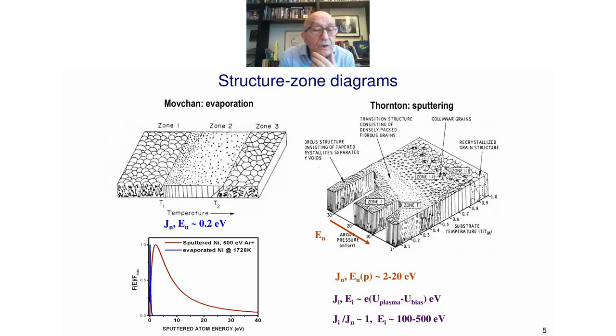Structural evolution is conveniently described by structure zone diagrams. The first one was introduced by Movchan and Demchishin, Ukrainian scientists from the Paton Institute, Kiev, for thermal evaporation, electron beam evaporation. There, as a function of the homologous temperature, the ratio of the substrate temperature to the melting point temperature, they characterized three zones. At very low temperatures, with practically no diffusion, films are rough and porous. At intermediate temperature, with surface diffusion, you have bulk-like properties with columnar growth, and at higher temperature there is bulk diffusion also.